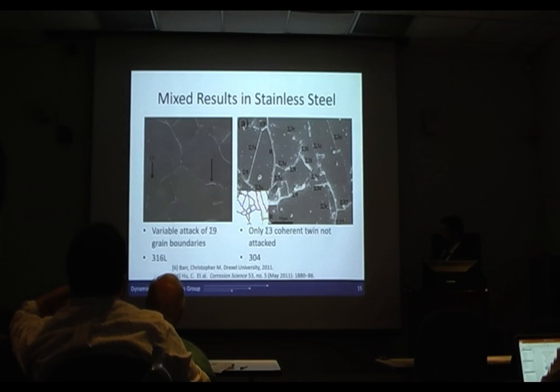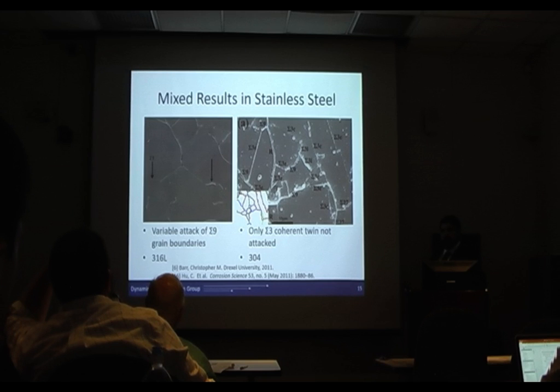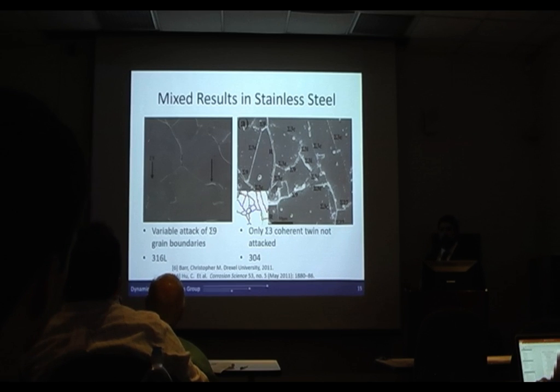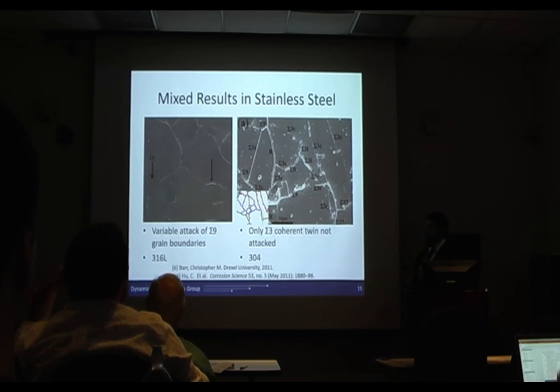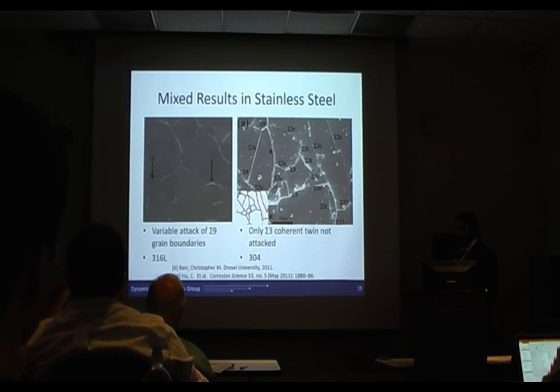Now, in stainless steel, the results have been a little bit more mixed. In this case, in stainless steel, we're mostly concerned about the corrosion resistance instead of the creep rate. However, on the left here, this is work by Dr. Christopher Barr here at Drexel. The two arrows denote sigma 9 grain boundaries, and you can see the one on the left did not corrode, the one on the right did. And they have the same misorientation because they're sigma 9s. However, they probably have a different grain boundary plane because of different corrosion resistance. Conversely, in Hu's work on the right, in a similar type of test, he found that only the sigma 3 coherent twins were resistant to corrosion.